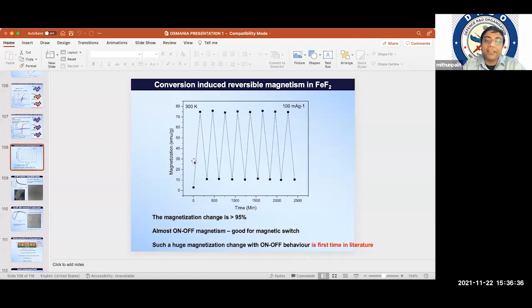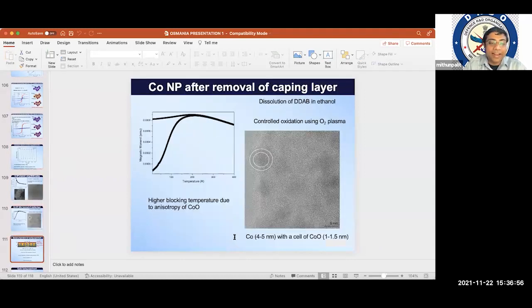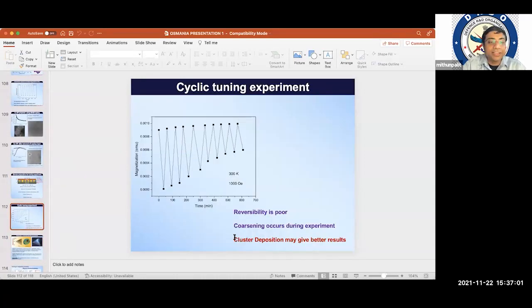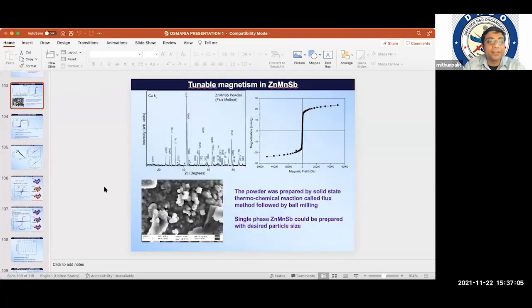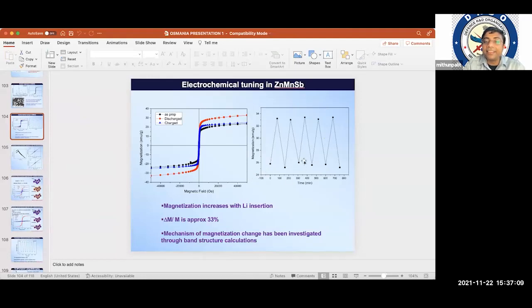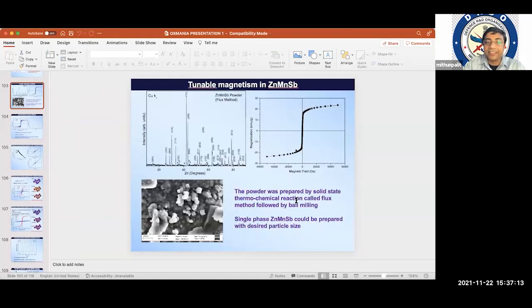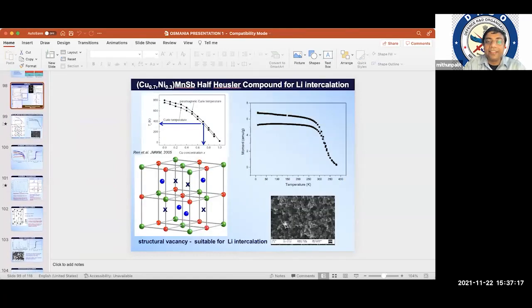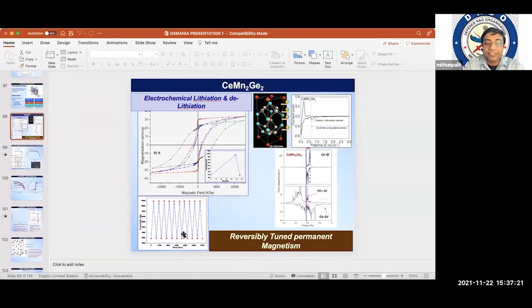You can see that when we are reducing the iron fluoride to iron by lithium ion, the magnetic moment increases. And whenever I reverse the potential, it comes back to iron fluoride once again. In the next cycle, again the same thing happens. So they are completely reversible. Only in one case, this cobalt nanoparticle, because of such a fine size, we could not control it so reversibly. But otherwise, if you see the other results, like this one, that change in the magnetic moment is almost reversible over several cycles. Similarly, this one, the coercivity change. You see this plot over here. Over several cycles, the coercivity is going up and going down with lithium insertion and lithium removal from the cell.